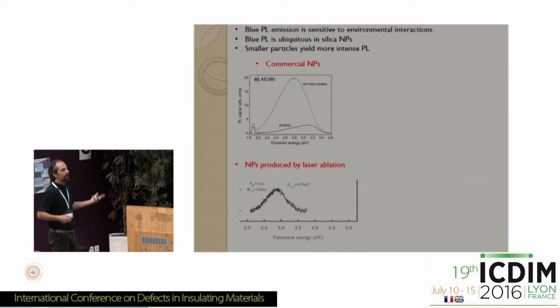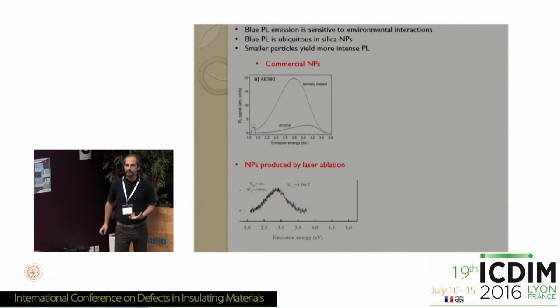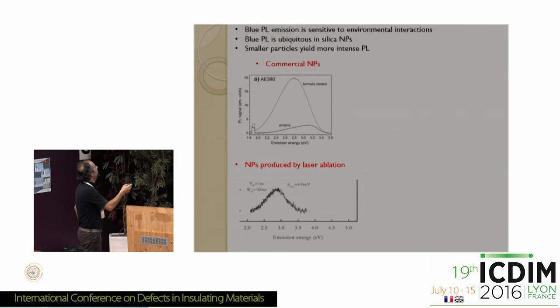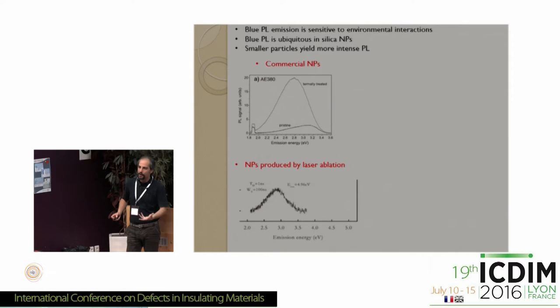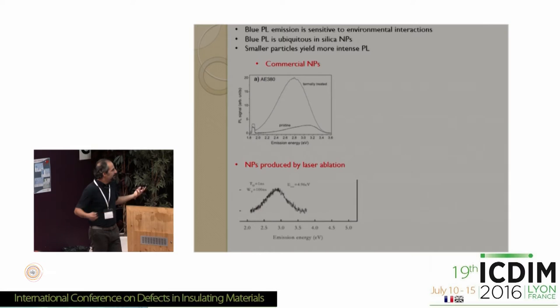Some general findings about this blue emission is that, for one, this is found more or less everywhere in silica nanoparticles. Here you can see the blue emission as we detected in nanoparticles produced by laser ablation in liquid phase. Here you can see the same emission as measured in commercial silica nanoparticles. So essentially, independently of the way the particles are prepared, this luminescence is usually observed.